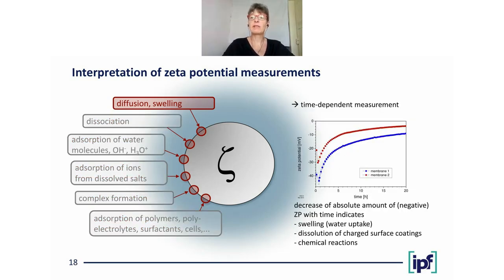For instance, with a time-dependent measurement, we can see swelling of a surface. If we bring a swellable, hydrophilic surface in contact with a solution, it takes up water. And when the water content increases, then of course the potential difference between the solid and the surrounding water decreases. The absolute amount of the Zeta potential decreases, as can be seen in the graph shown here at the right-hand side. Of course, there are other effects that lead to a time-dependent change of the Zeta potential, like for instance, the dissolution of charged surface coatings or chemical reactions. So it's always necessary to know the system we are measuring to understand what we measure.